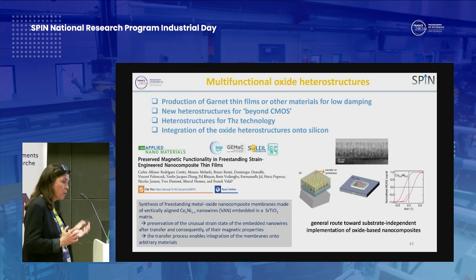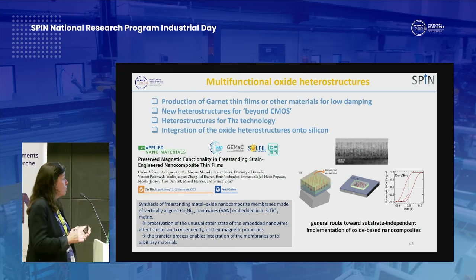So here, it's a recent example of the synthesis of freestanding metal oxide nanocomposite membrane made of vertically aligned cobalt-nickel nanowires within a STO matrix. So the unusual strain state and therefore the magnetic property of this nanowire are kept intact through the removal from the substrate and the transfer to another substrate, which opens the route towards substrate-independent implementation of oxide-based nanocomposites.